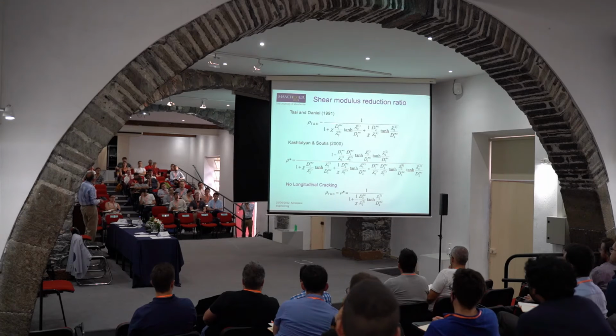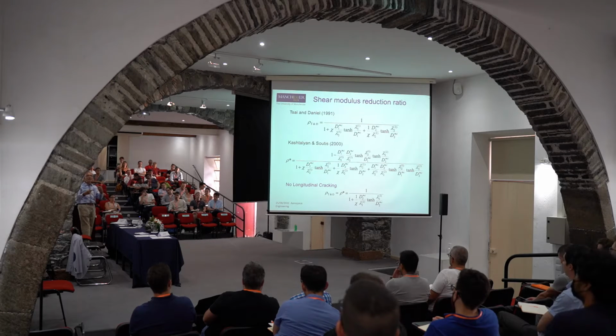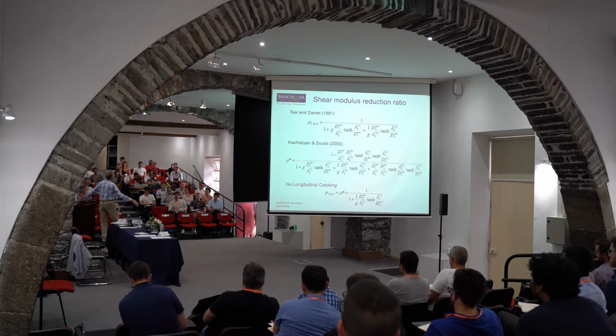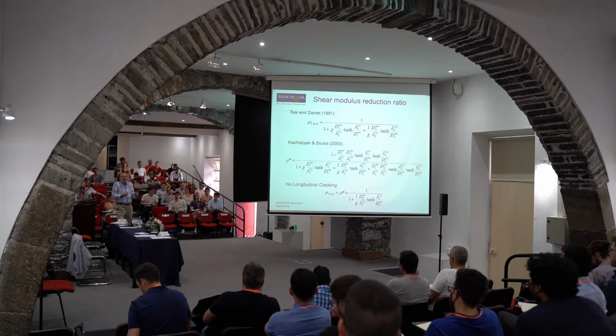And of course, most of the published papers out there, like say the top one, Tsai and Daniel, people still use. Most of the models, they focus just on the elastic modulus, E. While we know very well it's also the shear modulus and the transverse modulus and the Poisson ratio. When someone does an FE analysis and tries to account for damage and reduction of those elastic properties due to damage, they assume that I lose 10% of my axial modulus, 80% of my transverse modulus, 20% of my shear modulus, and another 10% of my Poisson ratio. And the problem is, in a cleft configuration, the Poisson ratio might go up. Might go up by 20% or 30% in the presence of damage.